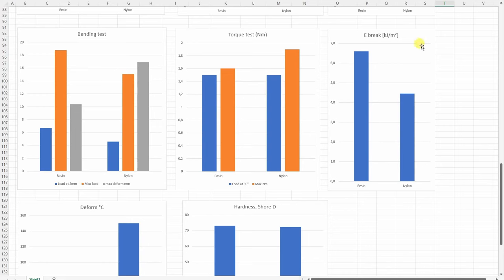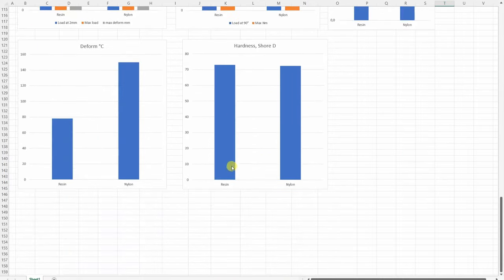And the impact test, so here the resin is more tough material, so the nylon is more brittle compared to this resin, but basically these are quite good values. Now the deformation, I couldn't really see, so obviously the deformation on the given temperature, so these are just approximate values. Interesting, you saw the resin was something like a rubber, but with that M10 nut on it didn't deform